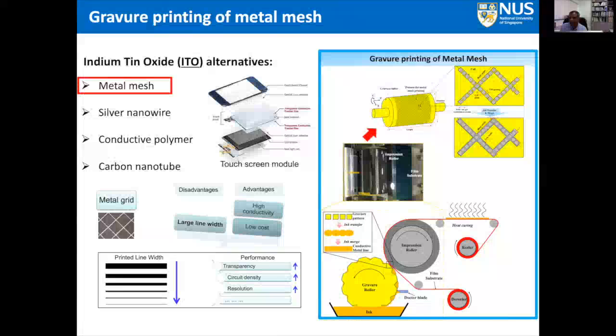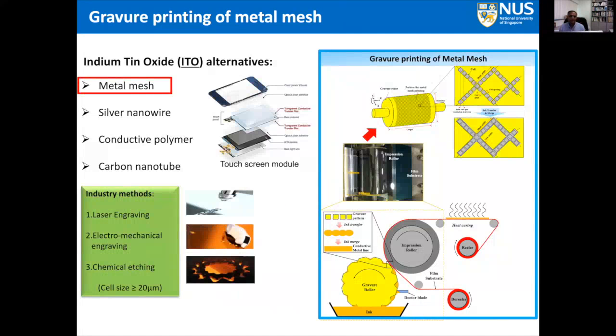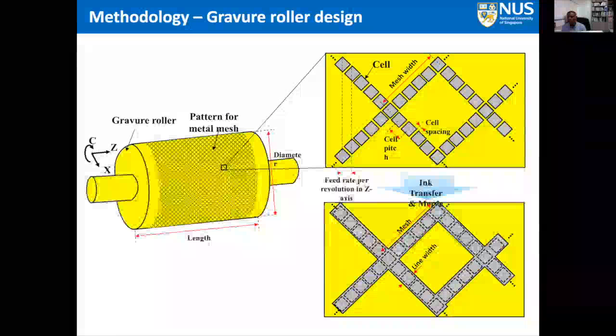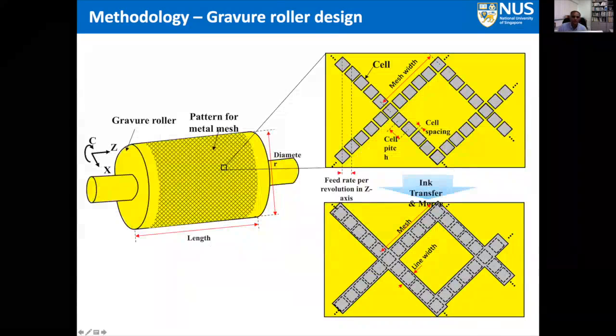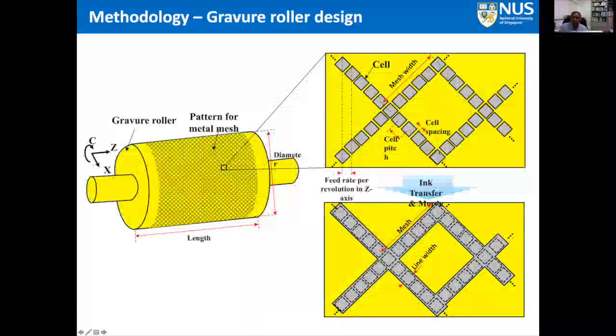So we went on to explore this, and the industry currently is using laser engraving, electromechanical engraving and chemical etching. But we wanted to see how we can replace this with a different methodology, and that is where this gravure roller machining comes into play. So this is the roller where you have the micro lines that are being drawn out, and these individual lines consist of hundreds of pixels, and these pixels have a very small gap here, and the ink is placed inside these pixels. And once they are placed and printed onto the plastic material, you see a very continuous line being produced. That is what is observed at the bottom here, which is shown in this image.